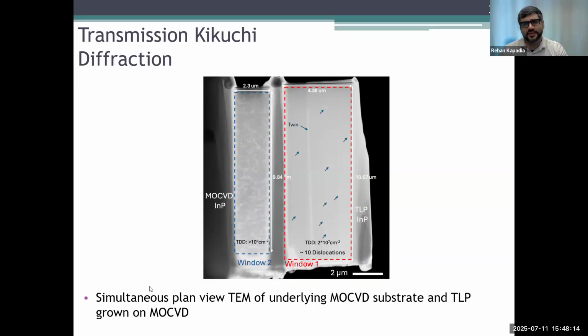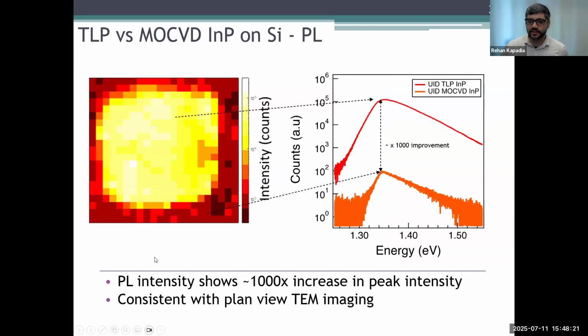And so then what we can say is that, all right, well, let's try to get some perspective on the improvement in quality. One of the things that we could do is take a photoluminescence map of the grown indium phosphide. So this templated liquid phase indium phosphide that's grown on top of the MOCVD indium phosphide. And we could look at the intensity, because intensity is a proxy for quality. And what we see is that we get something like typically 100 to 1000x improvement between the underlying MOCVD-based InP that I grew and the TLP-based InP that I grew on top of the bad MOCVD InP. And that relative difference makes sense based on the counting that we can do when we do plan view TEM, so it's consistent.